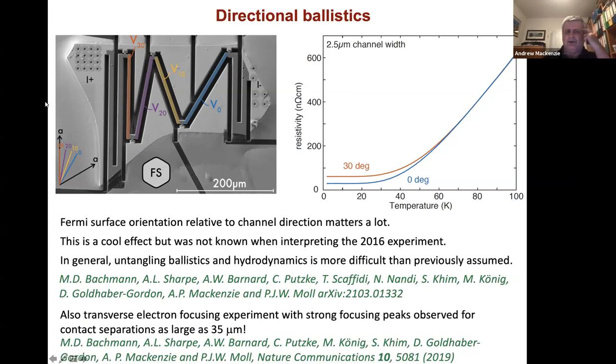Now, the fact that this is happening at all is one confirmation that the very long mean free paths I was telling you about must be true. But a much more direct one, although from a rather involved experiment that I don't think I've got time to explain in detail, was done and published in 2019, again in work led by Maya Bachmann. What she was able to show was a magnetic effect called transverse electron focusing. Crudely speaking, the basic scale for seeing that transverse electron focusing should be the electron mean free path. And we could see extremely good focusing results when we put the contact separations as far apart as 35 microns. If we could see these strong focusing effects with the contacts tens of microns apart, then there's really no other easy way to understand that than to say that the deduction that the mean free path is itself tens of microns has to be certainly order of magnitude correct.